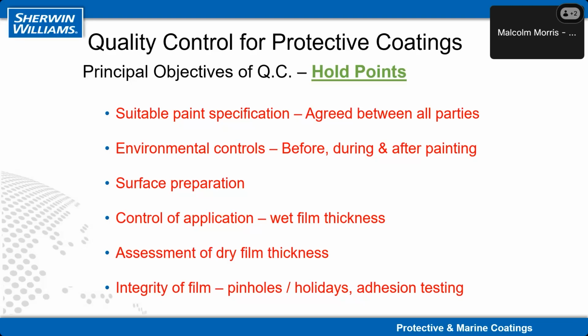So the ideal hold points with quality control should form a distinct view and approve systems. First of all, a suitable paint specification from either ISO12944 or the paint manufacturers, and agreed loadings for fire protection system. This has to be agreed between all parties, and everybody knows their responsibilities. Environmental controls before, during, and after painting. It's vital that paint is applied under the right environmental conditions of humidity, temperature, within dew point parameters, etc. If it's not, then paint will probably fail.